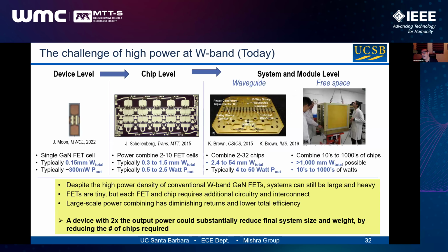So we chose, thanks to Paul Maki and the Navy advising us, W-band, because at W-band, the problem is you don't get a lot of power density at high frequencies, and efficiency is terrible. So basically, you've got to do a lot of power combining. Here are people who have done amazing work at W-band, combining 2 to 10 FET cells, 2 to 32 chips, and so on and so forth. And here you can get a huge 7 kilowatt transmitter from Raytheon with a gajillion chips weighing a gajillion kilograms. So we know the problem. The problem is size, weight, cost.